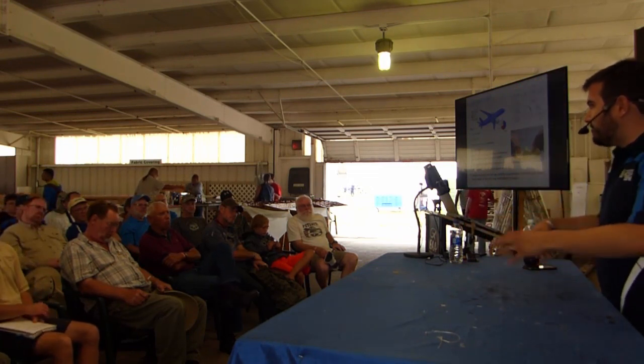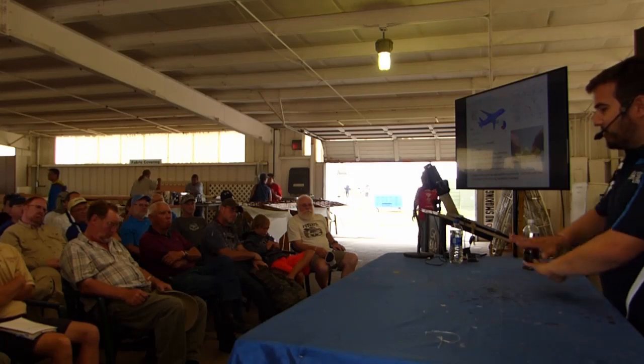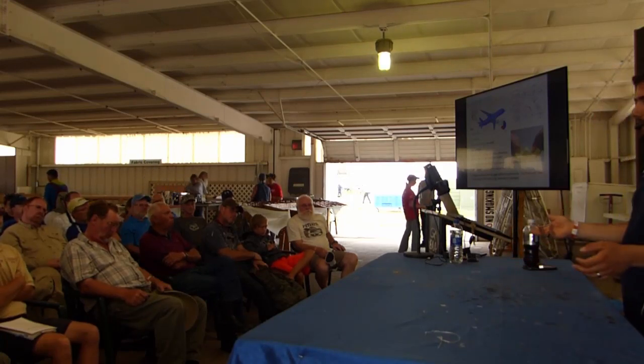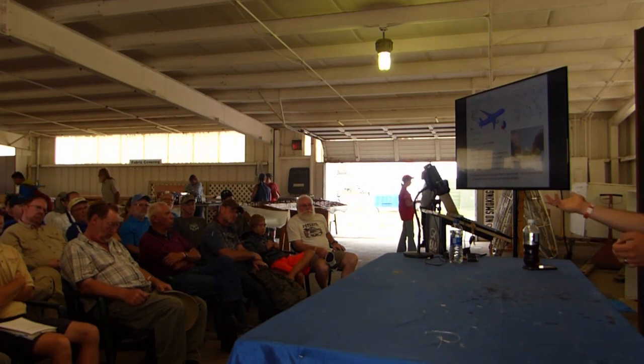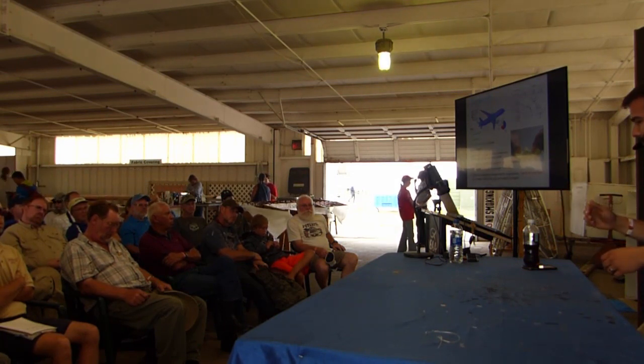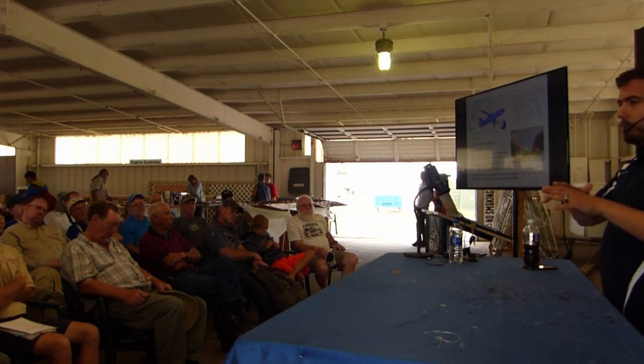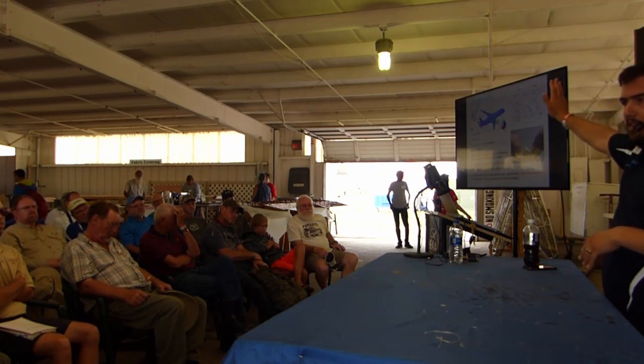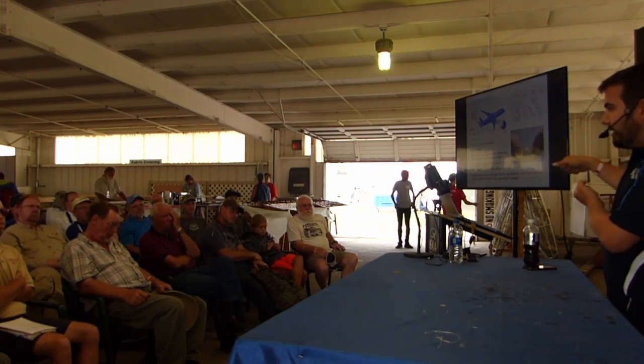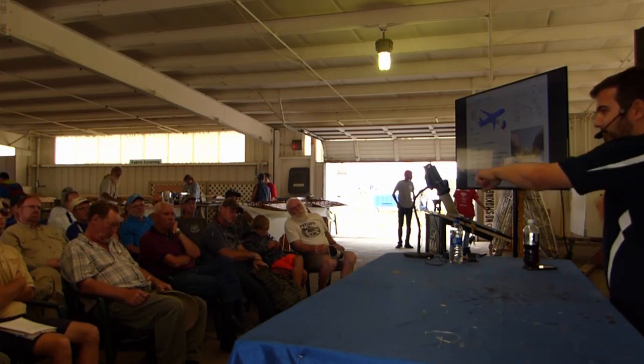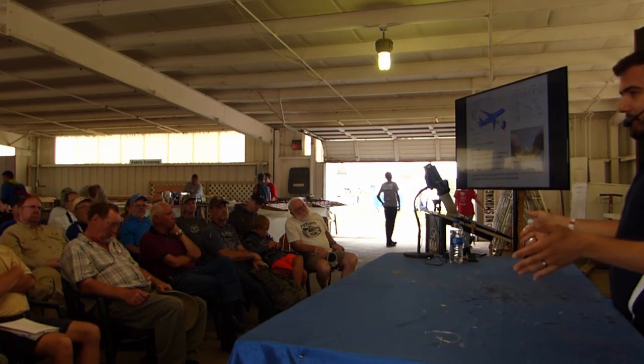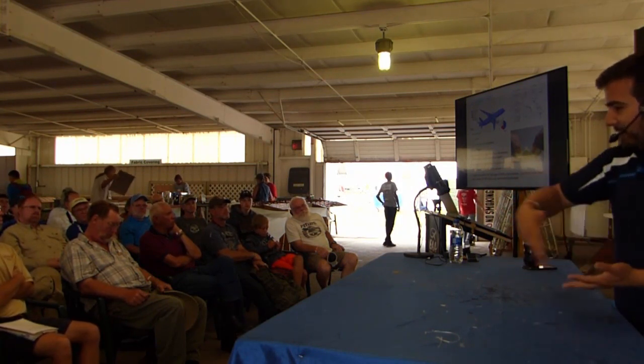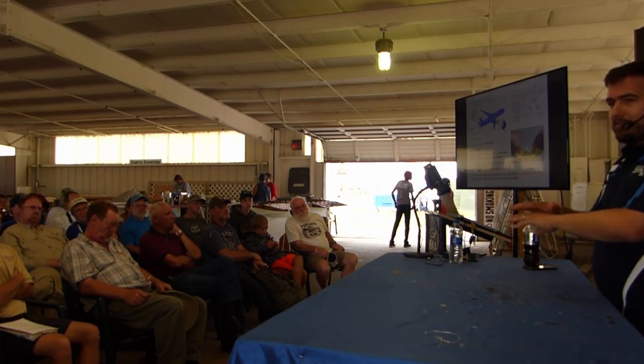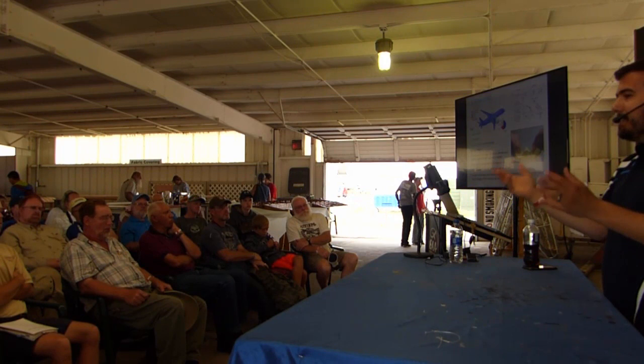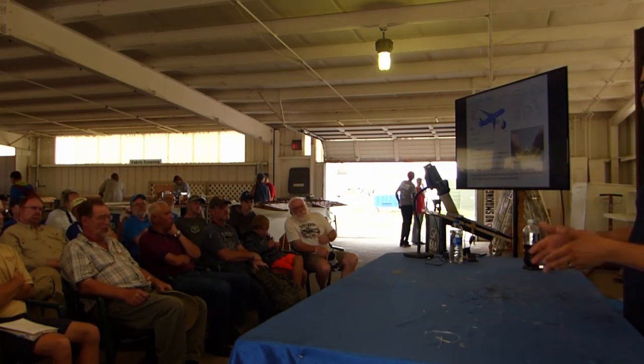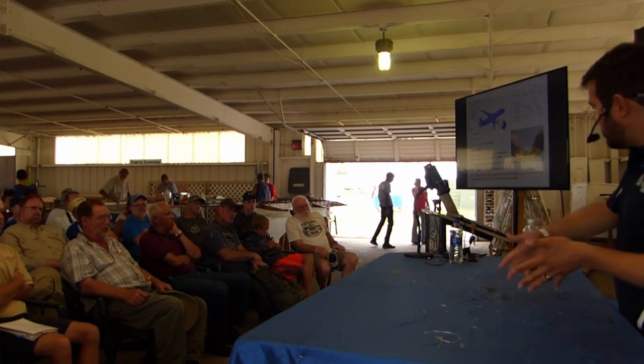So let's say I do 0, 90, 45, minus 45, and I do a few groups of 4 layers in these 4 different directions, 45 degrees apart. What I end up with is something that's about as strong as aluminum and a little bit lighter, or a little bit heavier if it's fiberglass, but it's generally comparable. Now here's the exciting part. Let's say I'm making a lower wing skin. The wing bends up in flight. The lower wing skin is in tension along the wingspan, so it's only really loaded along the wingspan. There aren't a whole lot of loads in the forward and aft direction on the wing skin. So I can take my fiberglass or my carbon fiber and take out most of the fibers that go this way, or most of the fibers that go at 45 degrees, and leave mostly fibers that go along the wingspan. A few more fibers I'll leave in there to hold it all together. But for the most part, I can just have fibers going this way.